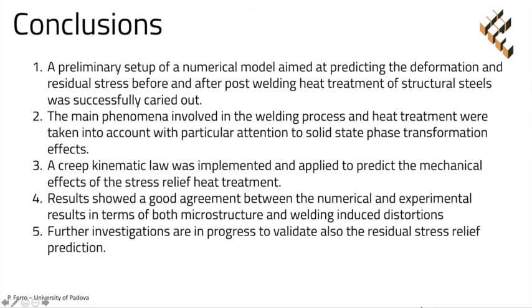Number 3, a creep kinematic law was implemented and applied to predict the mechanical effects of the stress relief heat treatment. Number 4, results showed a good agreement between the numerical and experimental results in terms of both microstructure and welding-induced distortions. Finally, number 5, further investigations are in progress to validate also the residual stress relief prediction.